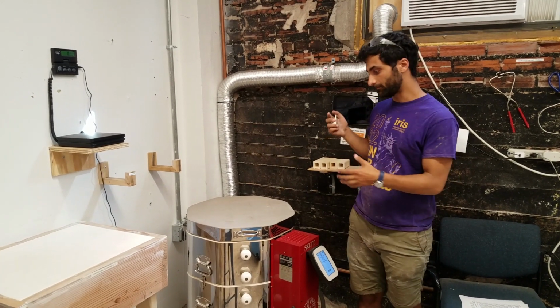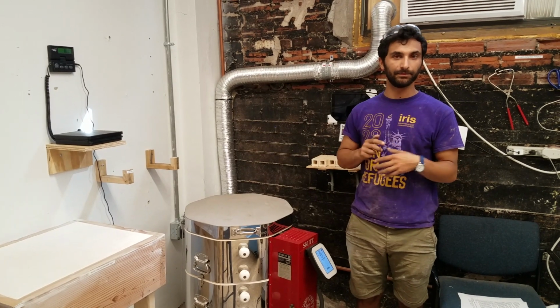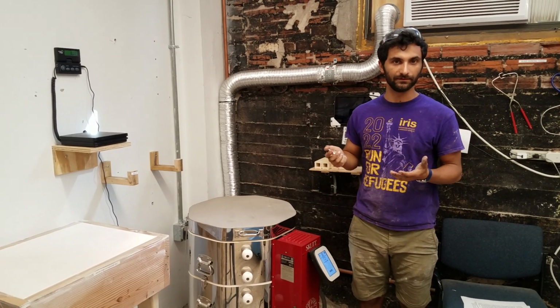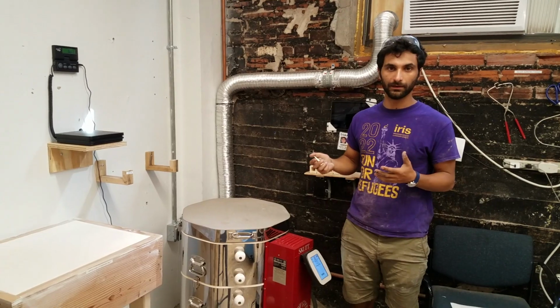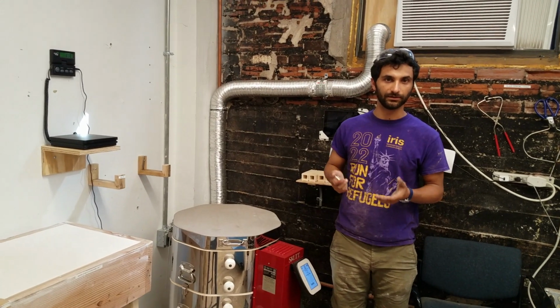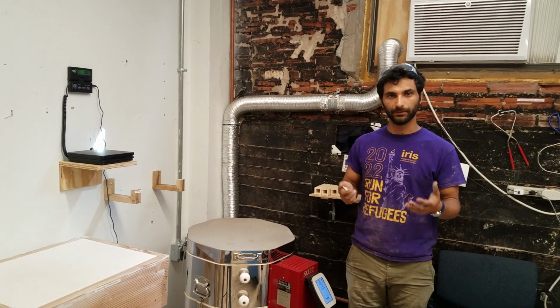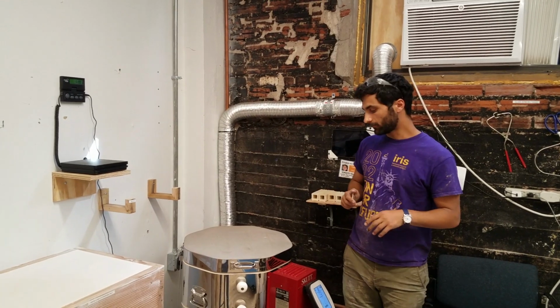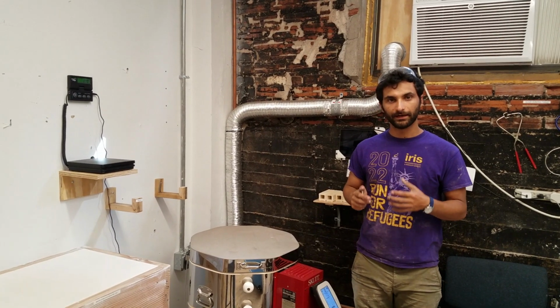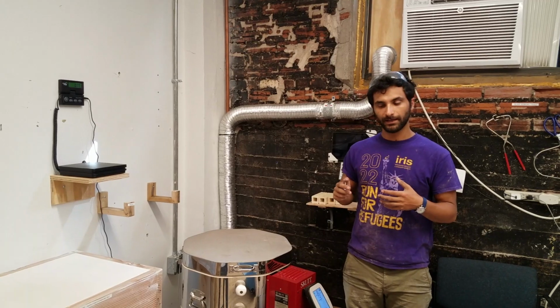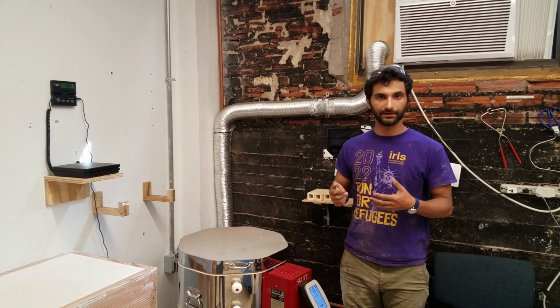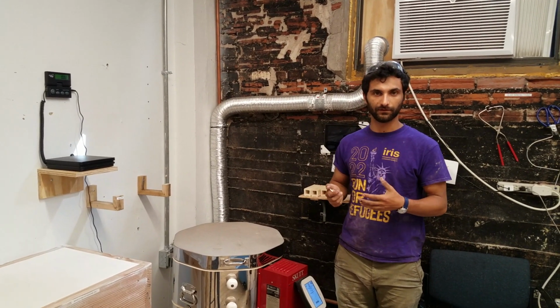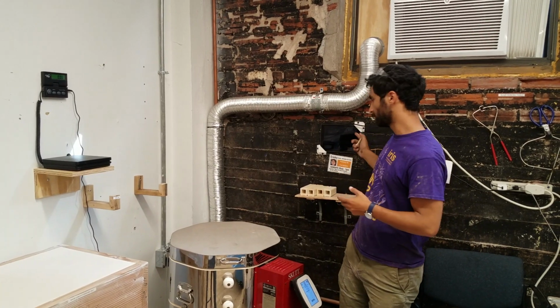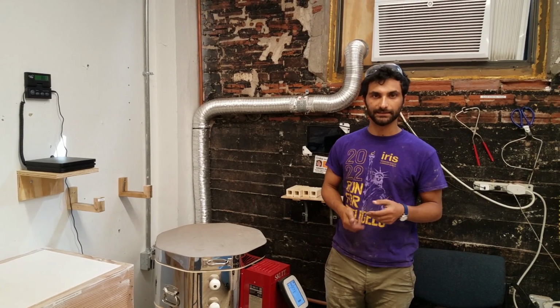Now if you have a bunch of people's stuff in there, then it's split up between everyone, so it's not so expensive. If you just want to do your one mug, then that's going to be pretty expensive, so it's a good idea to leave it on the shelf until there's more people's work to get fired at the same time. For the glaze firing, that goes faster even though it's hotter, and so it uses less electricity, so it's only about $5 for a firing. And we'll show you in a minute the kiln logs so you can see exactly how that is recorded.